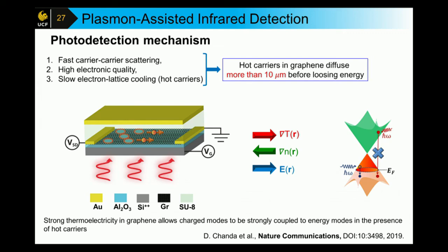So now we have a graphene that I patterned, and we do all the optics, which we covered yesterday, with the cavity and all these things. So you can create strong absorption on one side and weak absorption on the other side and create a thermoelectric voltage. That brings us to a technique where each time light comes in, I create a voltage out, because I couldn't follow the normal photodetector scheme using graphene, because it has no band gap.